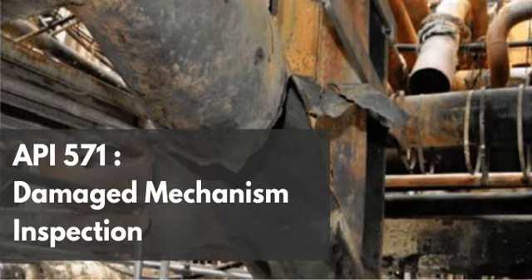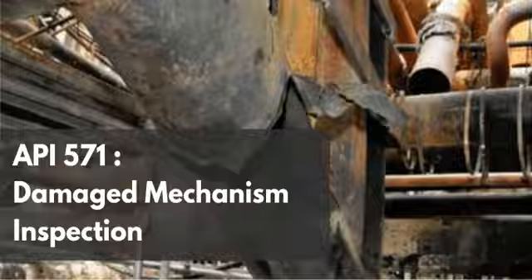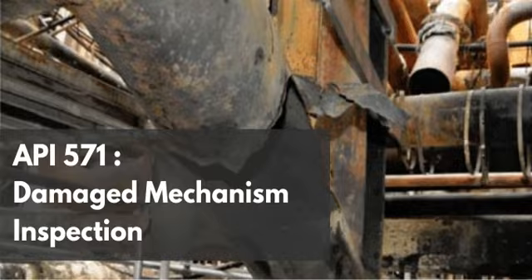What's fascinating here is how the degradation products chemically alter the environment on a molecular level. Well, it turns a benign treatment chemical into a highly aggressive corrosive agent. You have this MEA solution doing exactly what you want it to do, absorbing CO2. But under the wrong thermal conditions, that rich CO2-heavy environment facilitates a breakdown of the amine molecule itself. Wait, the molecule just falls apart? It degrades, it forms heat-stable salts and organic acids. So suddenly, the fluid flowing over your steel isn't just a carrier for acid gas anymore. It has fundamentally transformed into an acidic, corrosive medium that actively attacks the iron matrix of the steel.